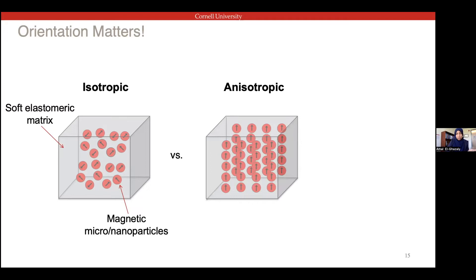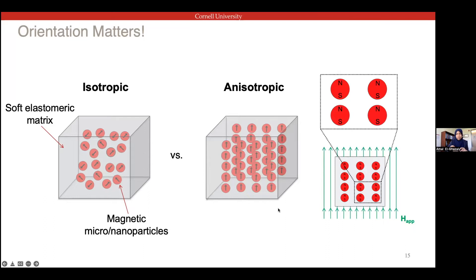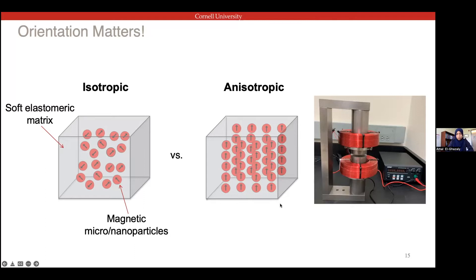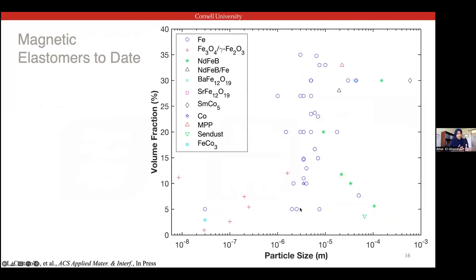Our work has been focusing on comparing the two. To create an anisotropic material, we apply a magnetic field while the elastomer is curing — we mix the particles in, apply a magnetic field, and local interactions between magnets create that nice chain-like behavior. This magnetic field is quite reasonable to produce in any lab; currently we're using 350 milliteslas, generated from a C-magnet built in the lab. We're also interested in producing the best possible display, so we want to give nanoscale or microscale texture.